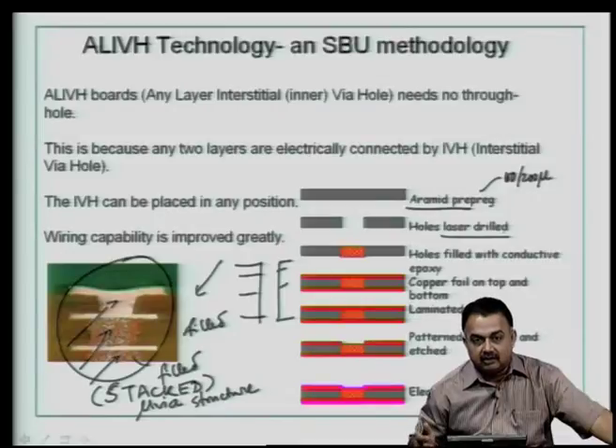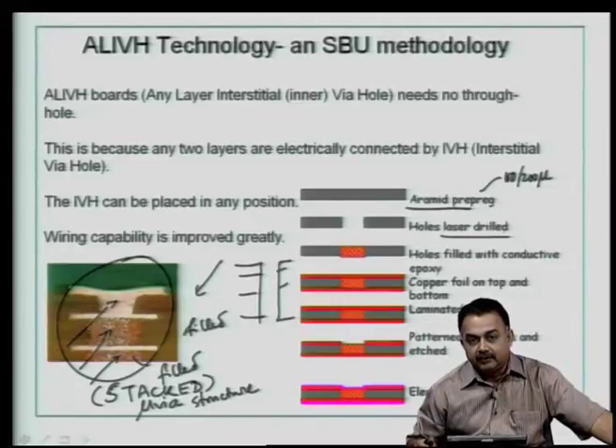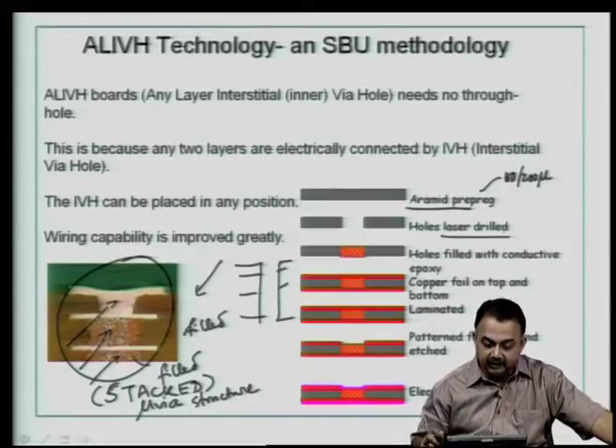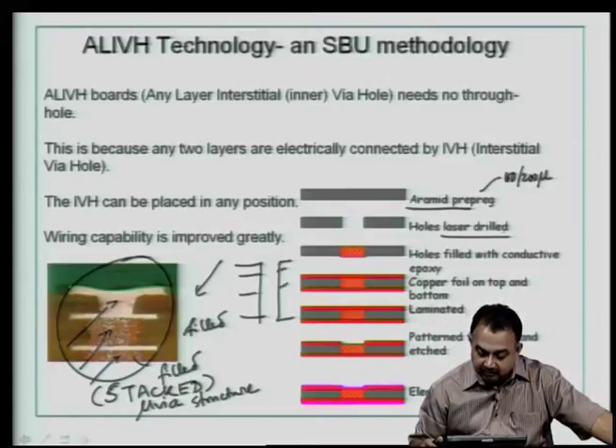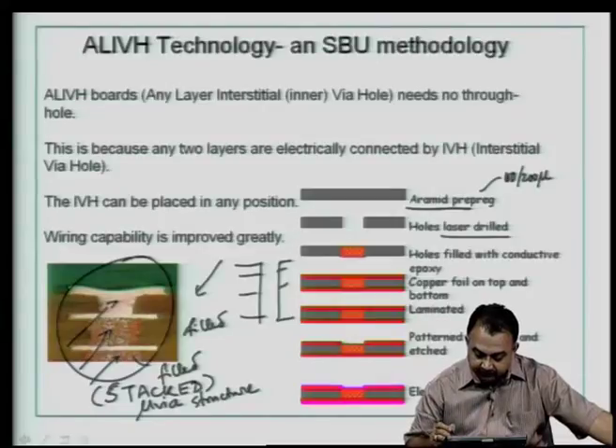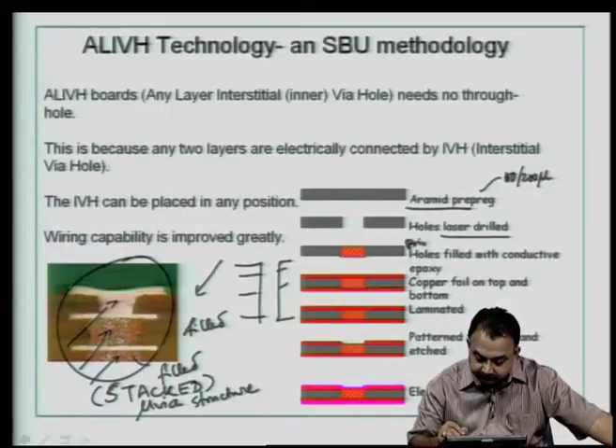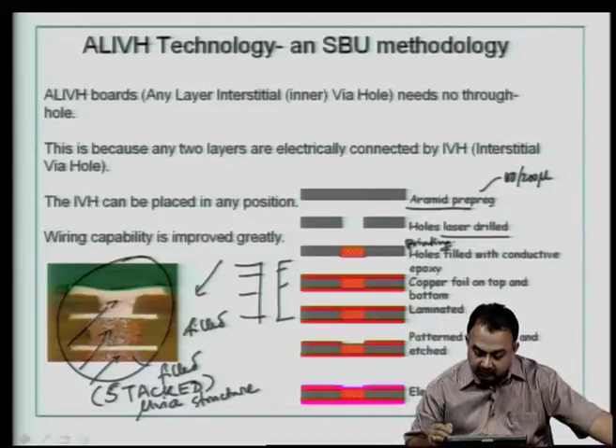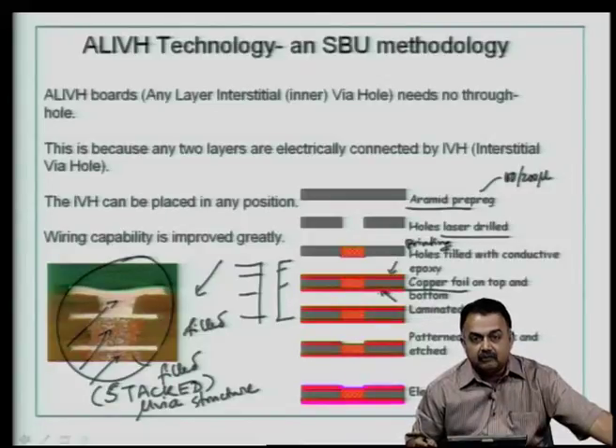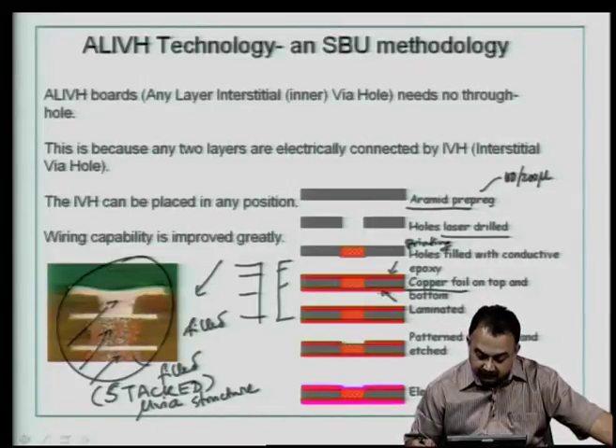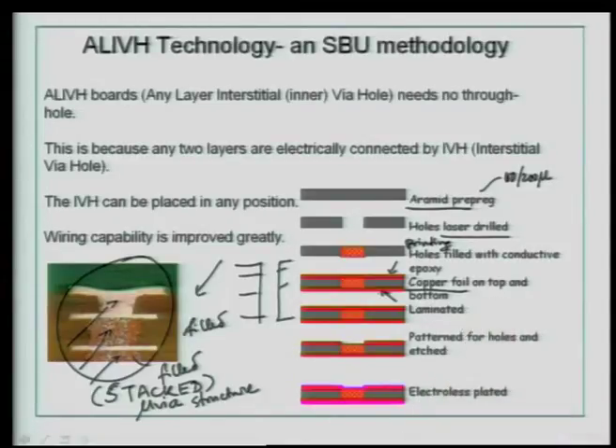So, you mix it with a suitable conductor material. It can be silver, it can be gold, or it can be silver copper or copper alone. It can be finely dispersed, very fine small particles dispersed in this media, and then they can be screen printed or stencil printed into the via structures. You can see here that after the printing process is over, copper foil is taken on top and bottom. So, now you decide what kind of thickness you want. It can be a 100 micron foil that you can put wrinkle free, and treated copper is now placed on top and the bottom, and now this structure is laminated.